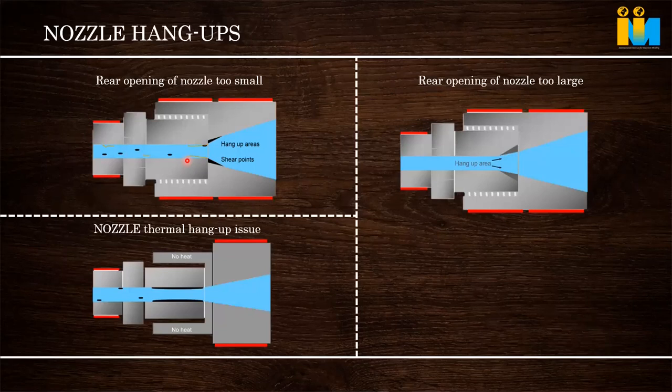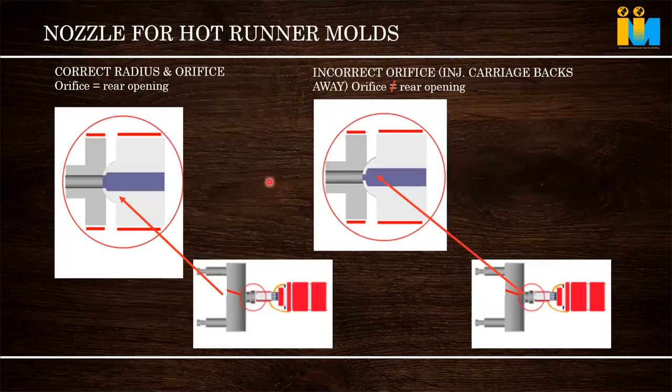It is like the runner and part we discussed. So this is for hot runner. We have discussed that in a normal mold, the sprue bush inlet diameter has to be a little bit bigger, 1 to 1.5 mm bigger than the machine nozzle diameter, so that the sprue bush easily comes out. It will not make an undercut and stay there fully.